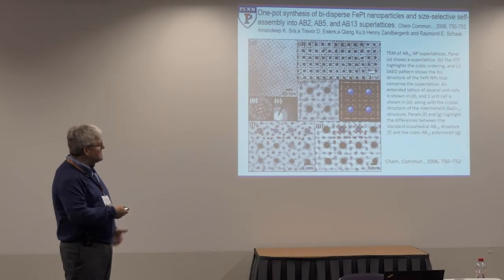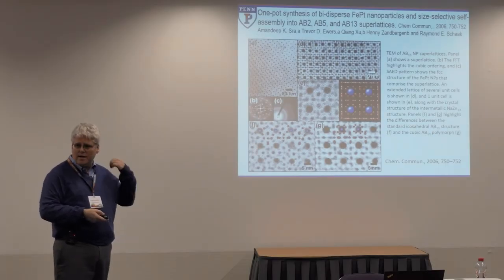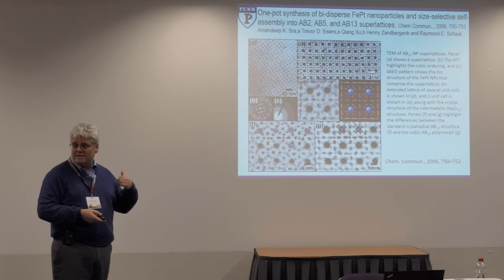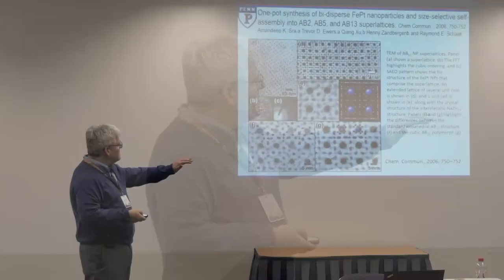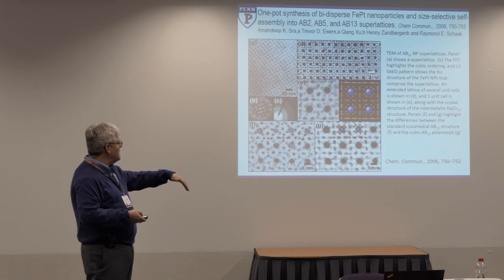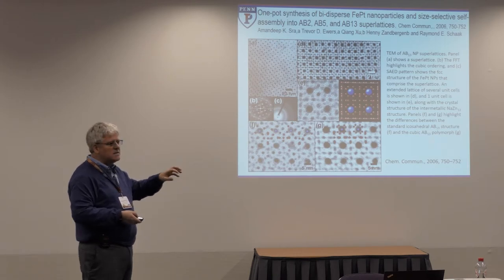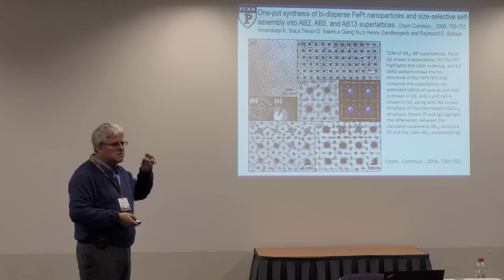So it turned out that a synthesis that generally produced just a single component system had accidentally had a secondary nucleation event, very much like the geologic example that we discussed before. And so naturally from that process, they identified the same binary phases that we had been working really hard to make by our design methods. And this was a sobering fact. It's a humbling experience when you realize this piece. They're very good chemists too. But it's the fact that these systems are not rare events. They're actually thermodynamically quite a good solution to the efforts to try to optimize the packing.